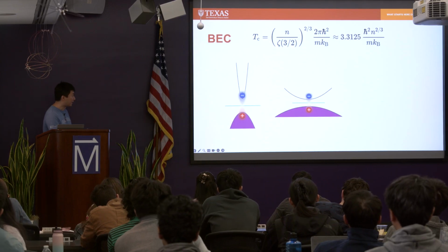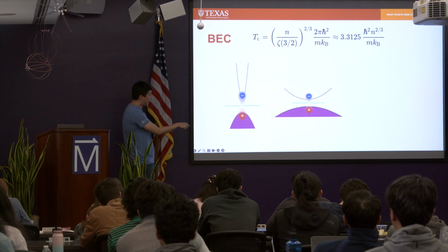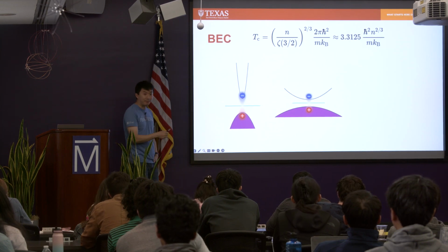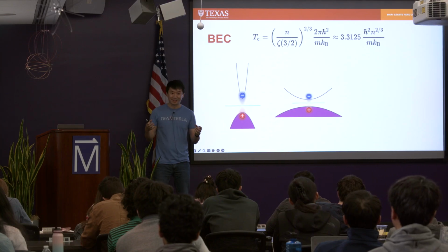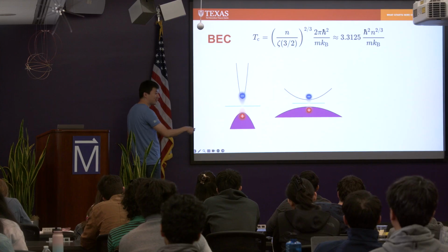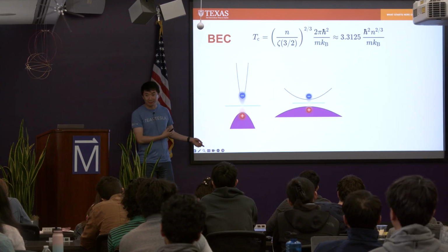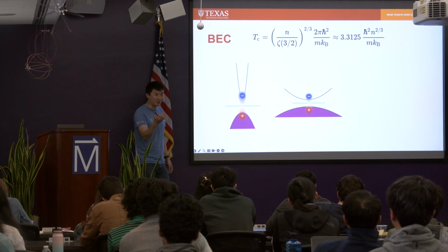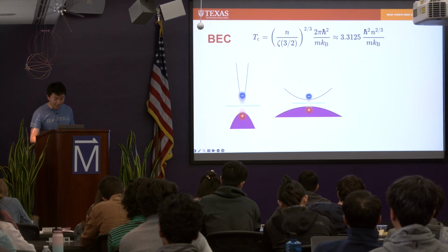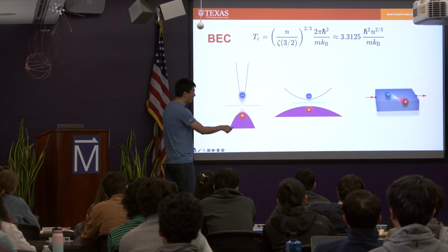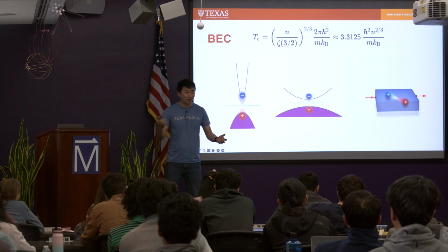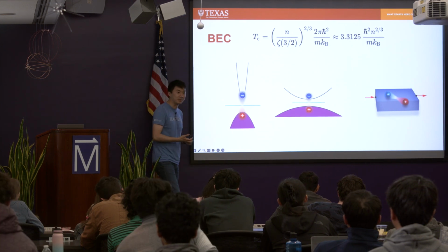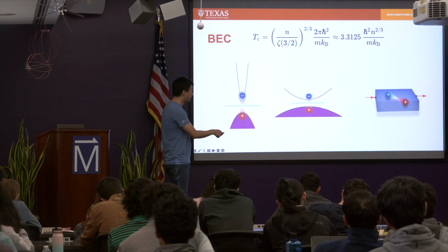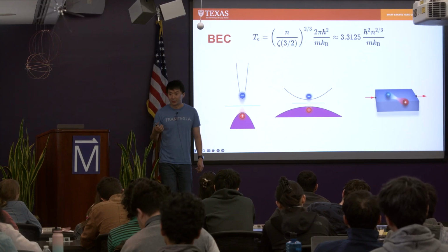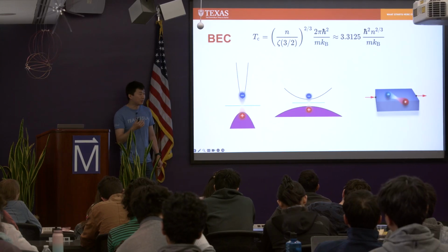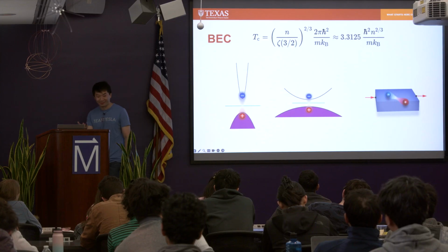Of course, there's another issue that in this picture, the electron and hole occupy different energy bands, but they coexist in the same physical space, right? So there's nothing that stops the electron from jumping back to the valence band and recombining with the hole, which means that the exciton lifetime is really, really short, right? Which puts an extra constraint on observing the condensation. And then, of course, there's a more practical issue: when electron and hole combine, right, this composite boson is overall charge neutral. And we rely very heavily on electrical transport measurement to detect quantum phenomena, which means that this condensate will be an insulator, right? You cannot really do electrical transport measurement to detect the dissipationless mass flow, which is inconvenient, right?